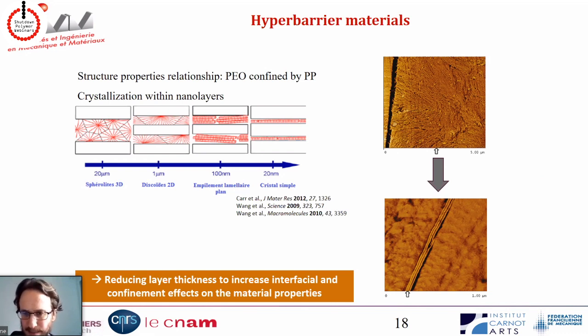And because this lamella is really well oriented, the gas molecule has to follow a bigger path to find a hole in this lamella. Here it's isotropic, so the gas molecule can find its way through the exit in the amorphous phase quite easily, while here it's really like a wall, so it has to go all this direction till it finds a really weak spot, then it can go this way. And so it will increase the path and really increase the impermeability of the system. And you can see that that's actually what happens.